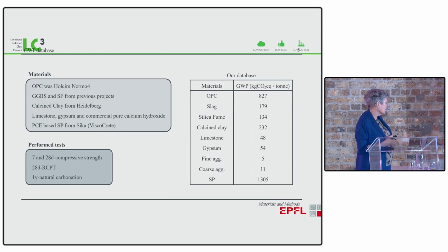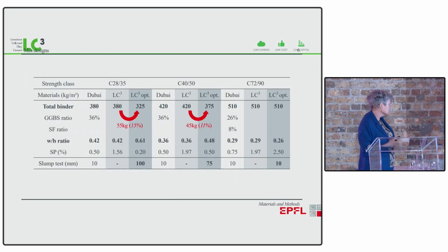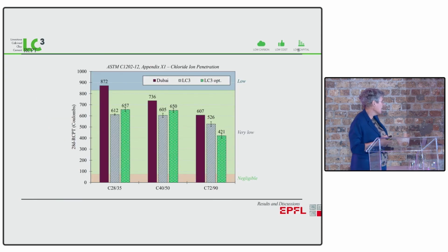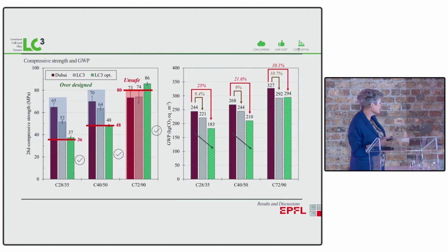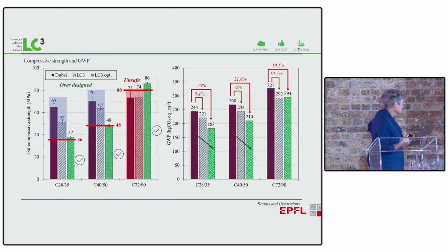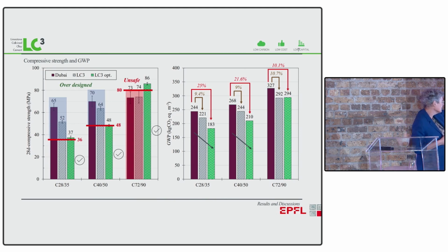So then we kind of looked at these mixtures again. We always did the life cycle analysis, and we saw what we could do by taking out some of the cement content, playing a little bit with the water-cement ratio, and now we can come up with mixtures. That's the chloride mixtures, which you can see that the chloride penetration by this RCPT method is always lower in the LC3, but what's more important here is the compressive strength and the global warming footprint.